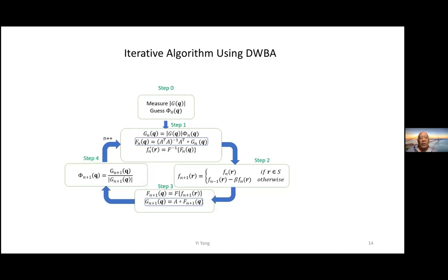And you think that you don't have enough information, but you do if you note that over the area detector, all the different QZs are there, as well as if you tilt the incident angle and have a range of incident angles and a range of combinations of KF and KI, KZI and KZF, you actually have enough information to solve these equations.